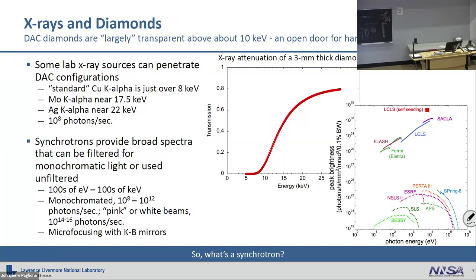And then you can take that percent deviation, widen it out again, and get a pink beam. The reason you do that really is to just get more photons. So now you have a broader spectrum, but you don't really care for your measurement enough, and it's fine to be pink. The white beam is basically just open the shutter and let whatever comes out come out. So the white beams are great when you want intensity. They're terrible for a lot of experiments.